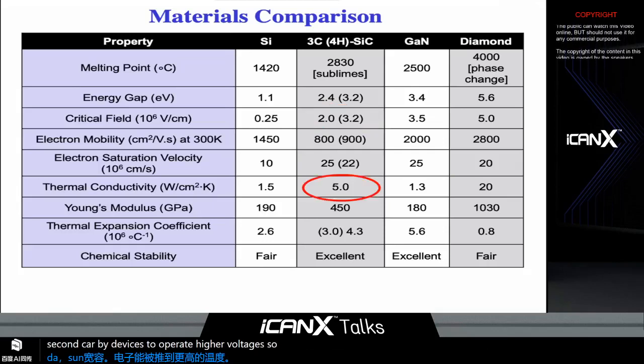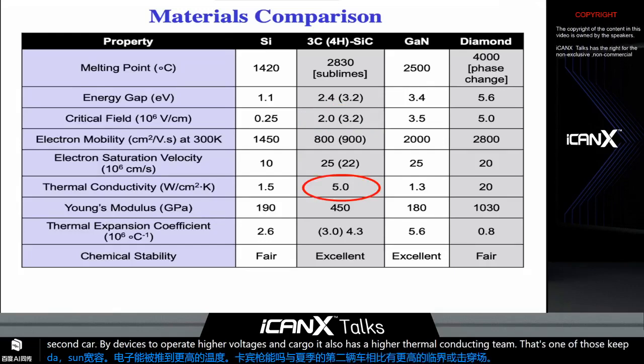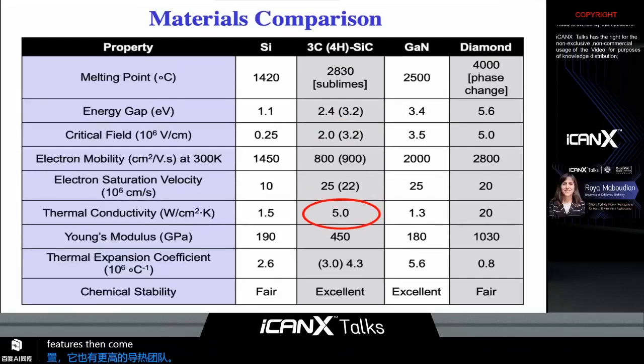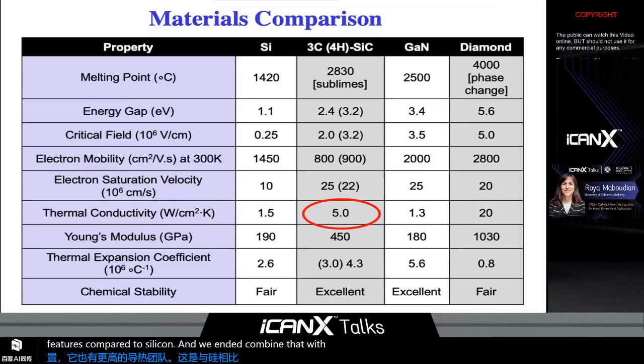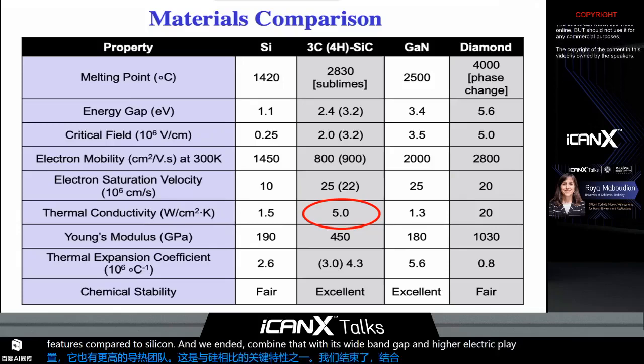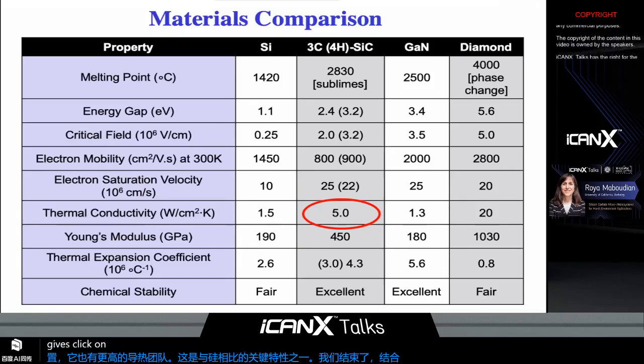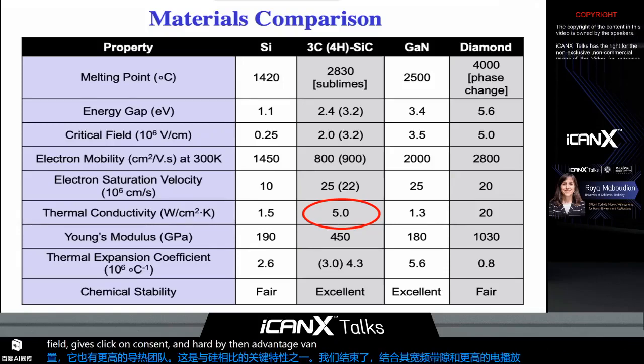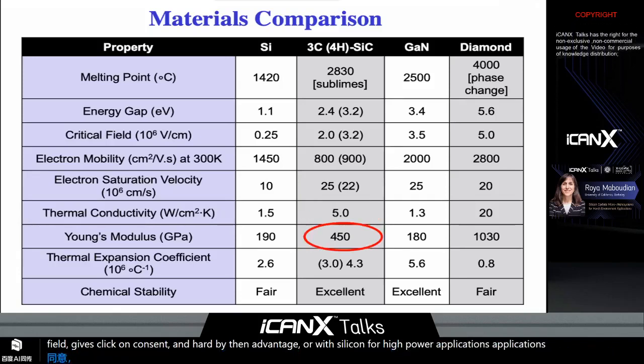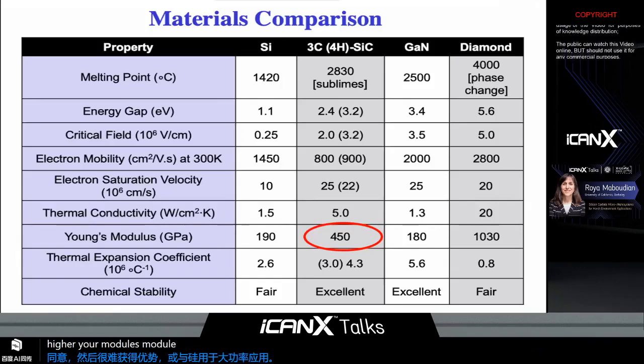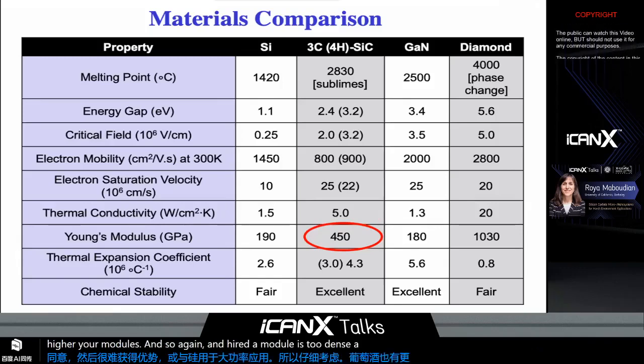Silicon carbide also has a higher thermal conductivity, and that's one of its key features when compared to silicon. When we combine that with its wide band gap and higher breakdown or critical field, it gives silicon carbide an advantage over silicon for high power applications. Silicon carbide also has a higher modulus than silicon and higher modulus to density ratio, which makes it an attractive material for high frequency MEMS applications.